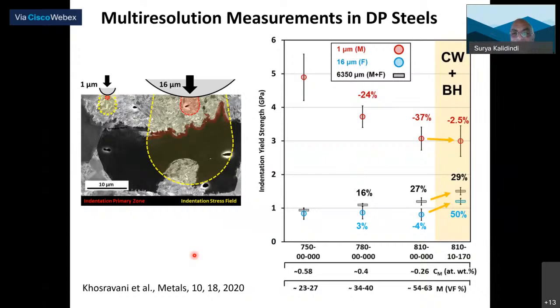So that is at the bulk level or effective level, but we can also do things at the local level. In a DP steel, we are getting properties in the martensite, using small indenters with the indenter radius shown here. So the actual indentation size is really, really small, much smaller than 1 micron. Typically the indentation zone size is about 1/10 of the indenter size. So you can actually compute how small these zones are.